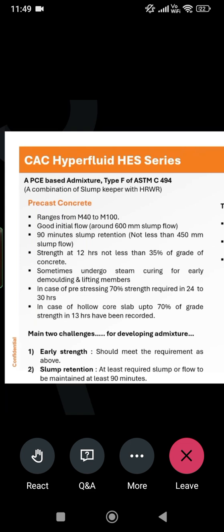In case of pre-stressing, 70% strength is required in 24 to 30 hours for pre-stressing. In case of hollow floor slabs, this is a very remarkable specification. Up to 70% of grade strength is required in 13 hours, as reported so far. So these are the precast concrete challenges, and the admixture challenge is that early strength should meet the requirement as above. Slump retention: at least the required slump flow is to be maintained for at least 90 minutes.